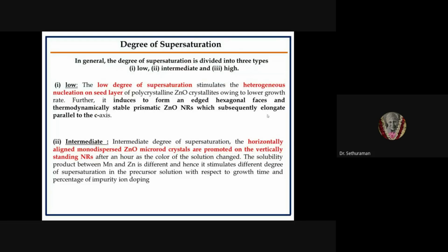The degree of supersaturation is low, intermediate, as well as high. A low degree of supersaturation means that it stimulates heterogeneous nucleation on the seed layer of polycrystalline zinc oxide crystallites, so heterogeneous nucleation is possible on the seed layer. Due to that uniform nucleation and also the lower growth rate, we have obtained beautiful vertically standing zinc oxide nanorods. Further, it induces to form edged hexagonal faces as well as thermodynamically stable zinc oxide nanorods, and these nanorods are elongated parallel to the C axis when the degree of supersaturation is very low.